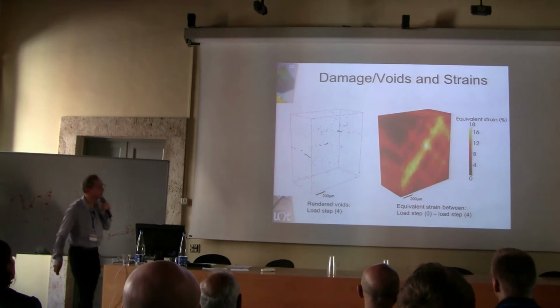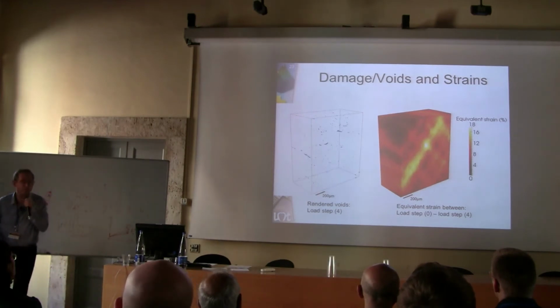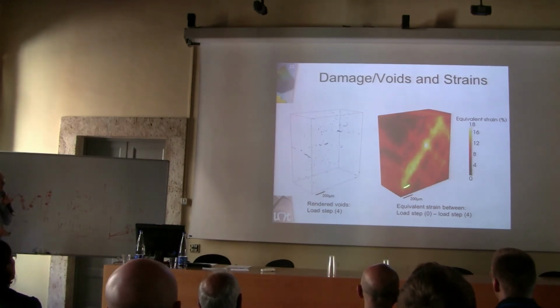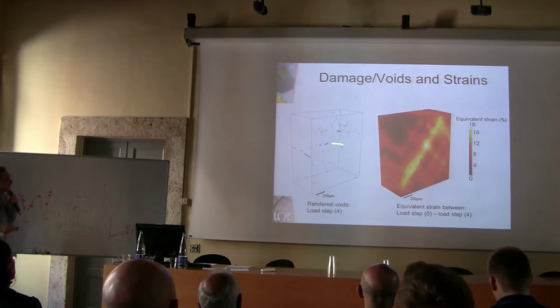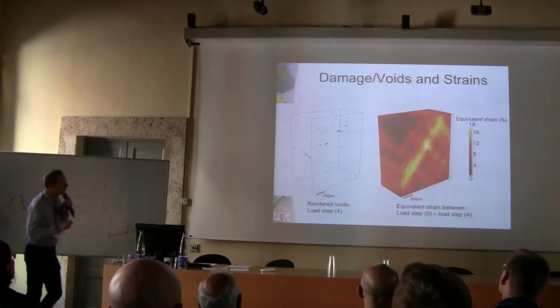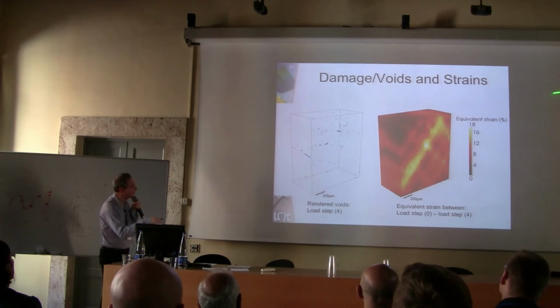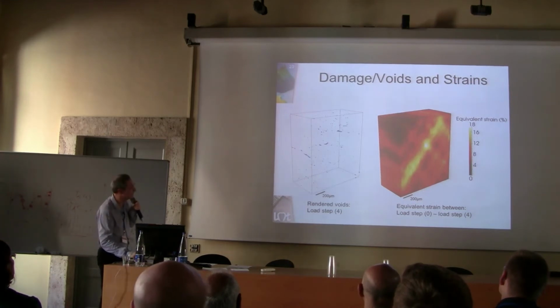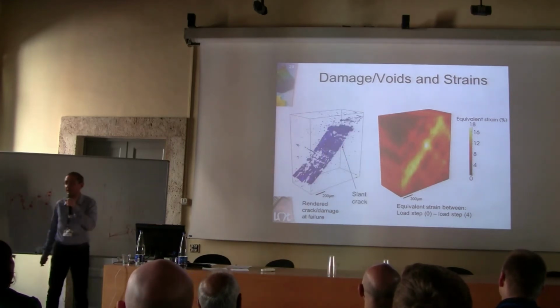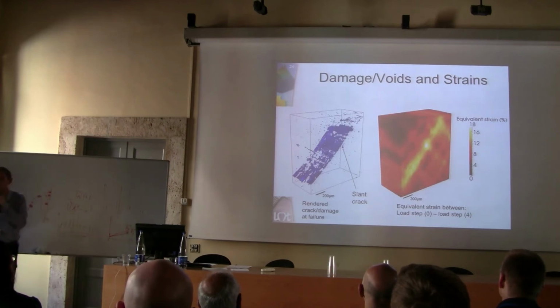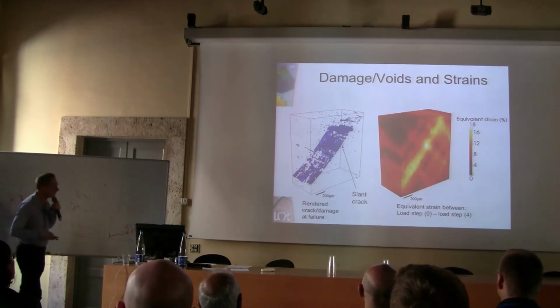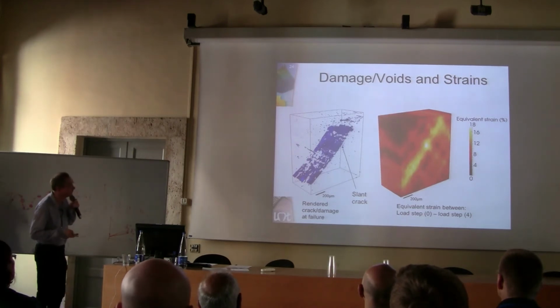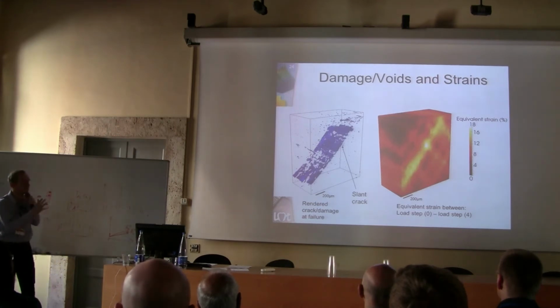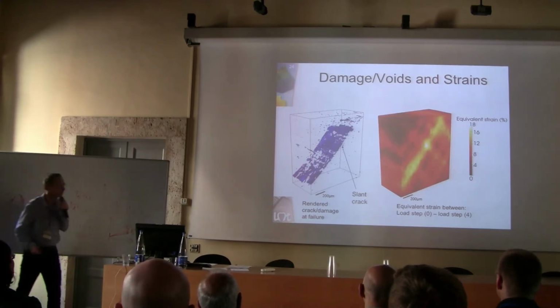And this is the final calculations that we could run, where you see one of these bands that is taking over. Again, a little bit more damage activity, but not correlated to these straight bands, which eventually led to fracture. This means that in this particular case, you could clearly prove that the driver behind this phenomenon is plasticity.